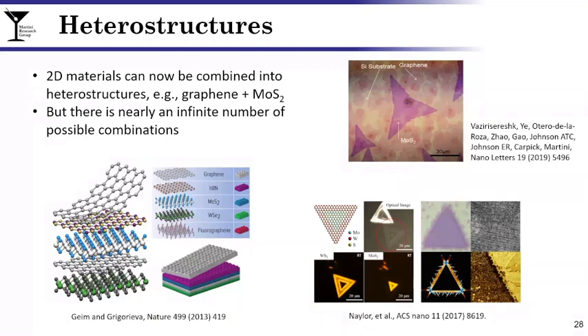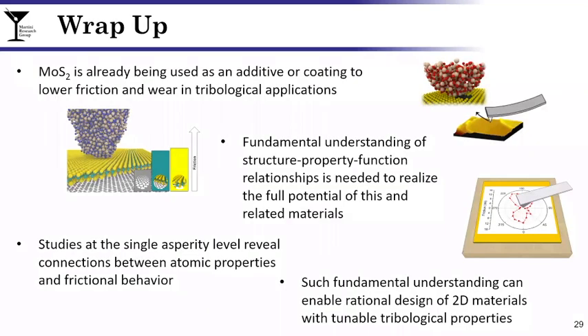So to wrap everything up, MoS2 is already being used as a lubricant additive as well as a coating. It already lowers friction and wear for tribological applications. One of the challenges for using MoS2 and similar materials is that their performance really is highly dependent on almost everything. And it's a huge challenge from an engineering design perspective to design with all these kind of unknowns. So the approach that I've presented here, and I hope I've convinced you of, is that you can break these very complex things down into the single unit of friction, the single asperity, which is realized using the AFM and complemented by molecular dynamics.